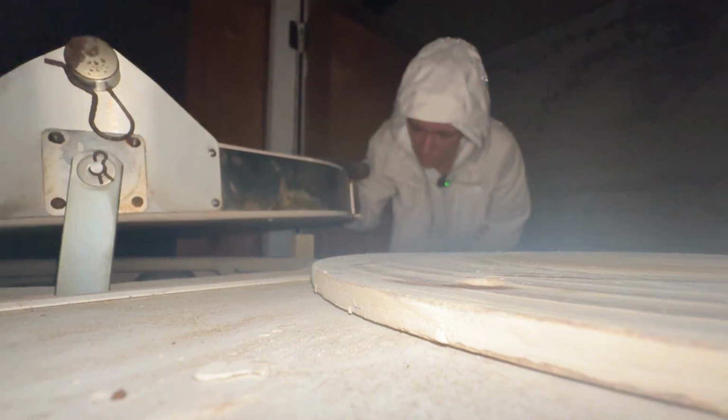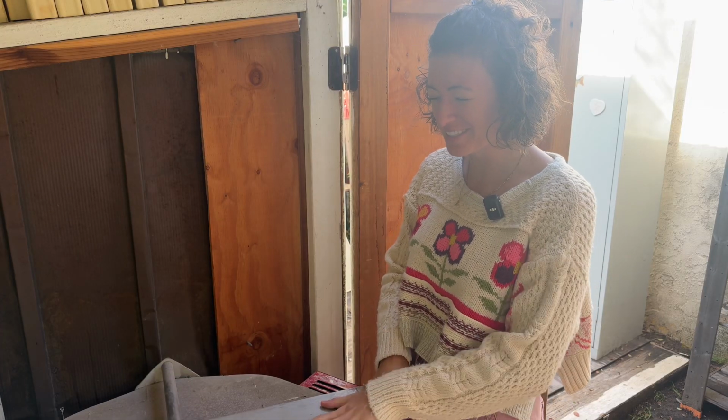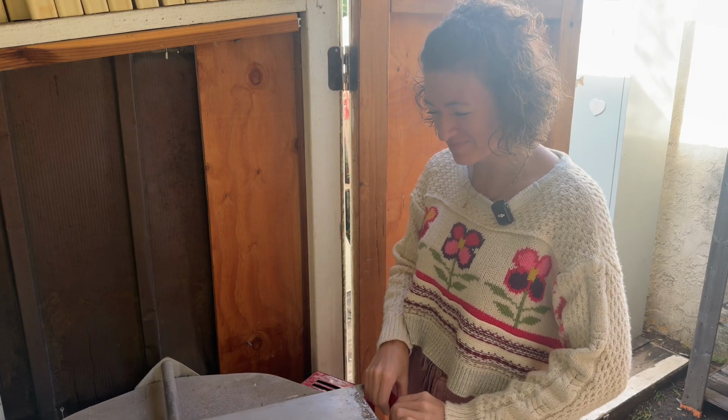And then we'll just... So let me explain a preheat. The kiln is going to slowly be brought up to 200 degrees, and then it is going to hold at 200 for 8 hours. After 8 hours, the kiln will then turn on and complete its firing. In this bisque kiln firing, I am going to cone 05. Sometime probably on Saturday morning, I will unload and we will see what survived. Please be good. Please don't let there be any explosions.